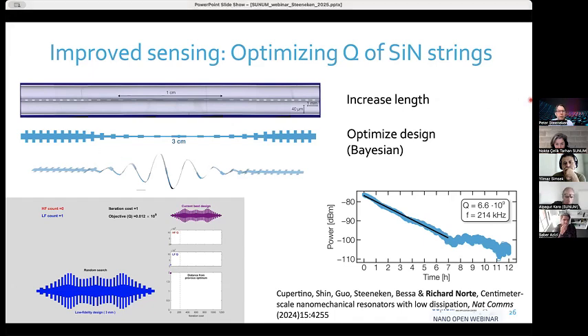Yeah, that's a very good question. But these devices, to reach these very high Qs, we have to operate them in high vacuum. So one of the challenges was actually to reach low enough vacuum in our vacuum system. So it's 10 to the minus 8 or maybe even lower millibar to prevent any air damping. So adding these does not increase the damping, but if you would do it in air or at higher pressures, then for sure you're right. Then they would actually decrease the Q factor. Did that answer your question or not? Yeah, thank you so much.